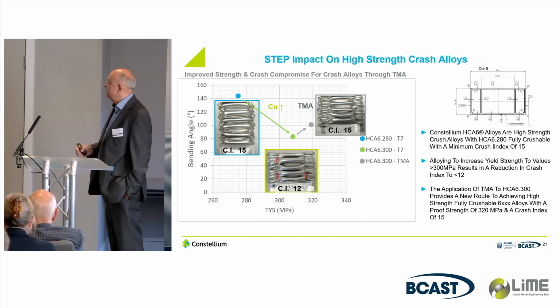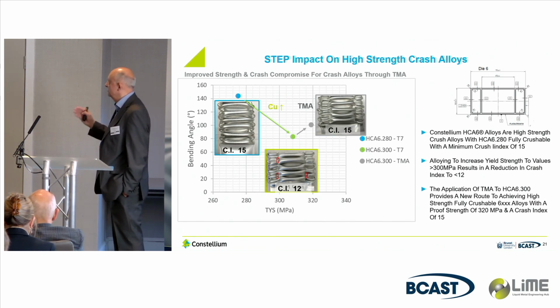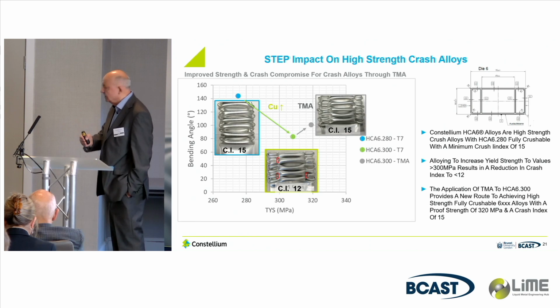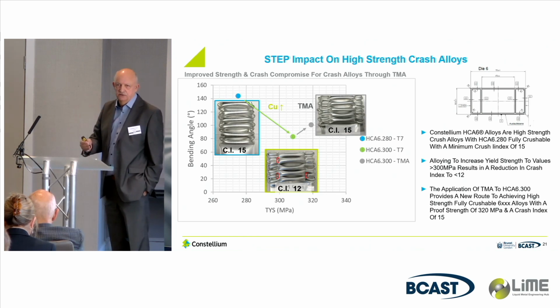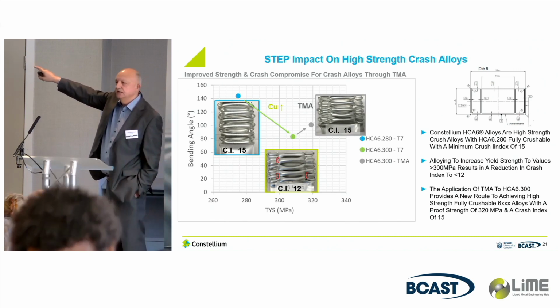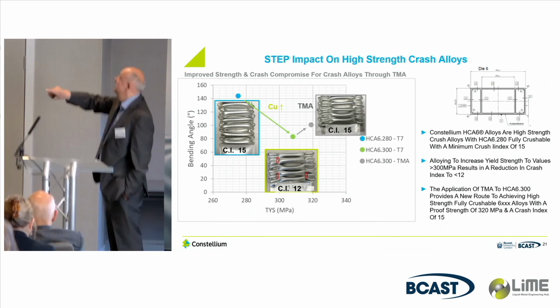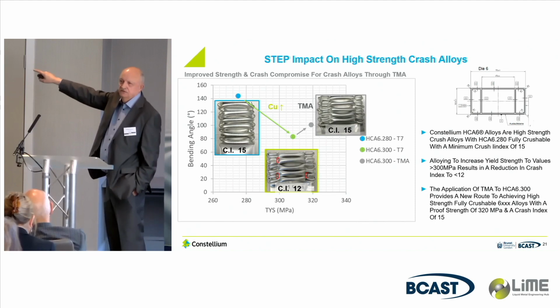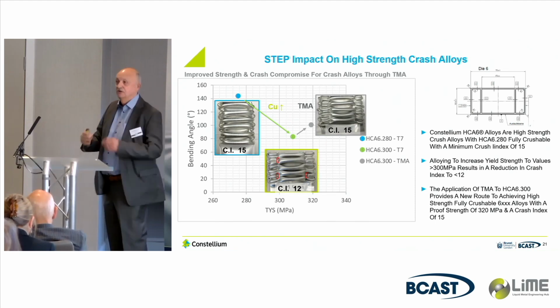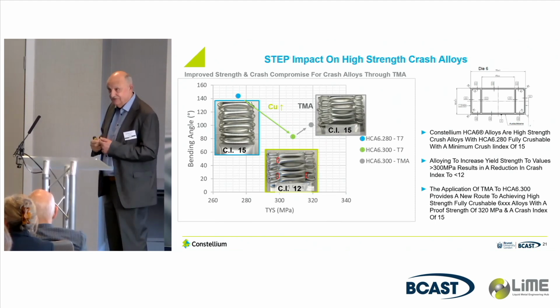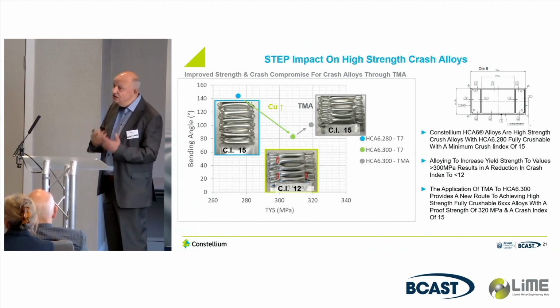What we found is when we go through a thermomechanical aging process, the step process, we can actually come off that curve, and what we find is that we can get up to 320 megapascals, and we recover the behaviour. We don't know why yet. It's part of the program we're working on, but it's really quite interesting.